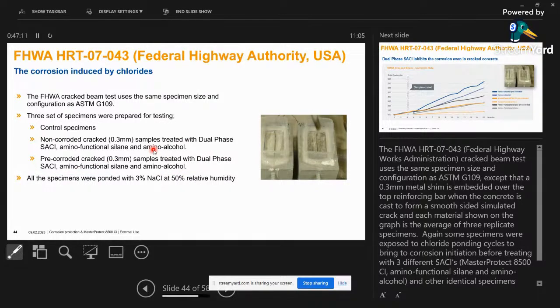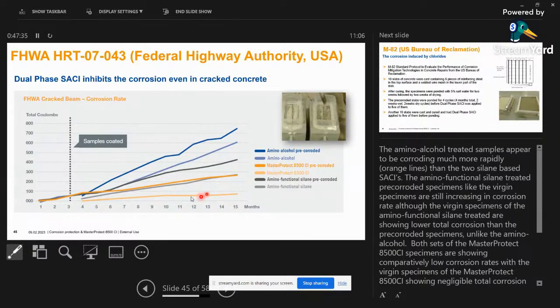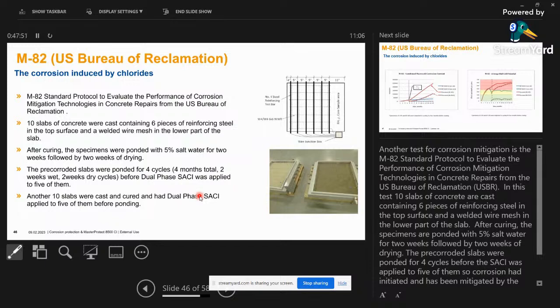Federal Highway Authority did a cracked beam test, using the same specimen. So they basically did the ponding and all, and then they took it out: non-cracked 0.3 mm samples treated with dual phase surface applied corrosion inhibitor, pre-corroded cracked 0.3 mm samples treated with dual phase surface applied corrosion inhibitor, and the ponding was with 3% NaCl solution. And you see here that the corrosion rate is so low compared to all other different types of impregnators which are available in the market. So it's a very direct measurement of how this system actually works. A very simple liquid, very simple to apply, but greatly effective in reducing the active corrosion in the embedded steel reinforcement.